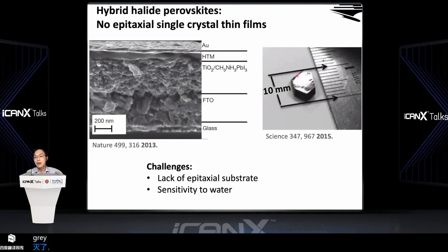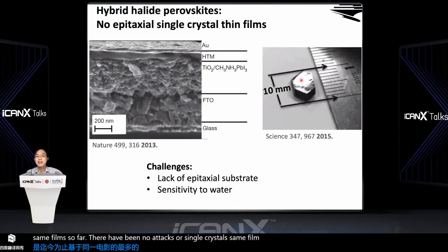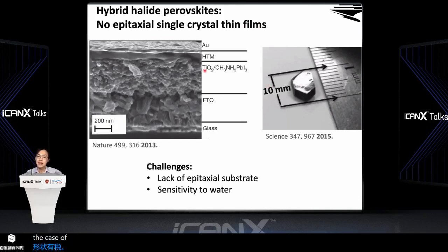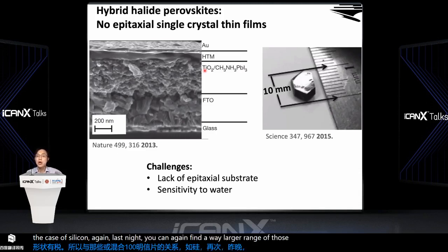And for bulk large single crystals, it's very difficult for them to be integrated onto these devices, which are mostly based on thin films. So far, there have been no epitaxial single crystal thin films based on those hybrid halide perovskites. And the challenges are twofold. The first thing is, it's very difficult to find a substrate that has an epitaxial relationship with those hybrid halide perovskites. As in the case of silicon and gallium arsenide, you can find a very large range of substrates to grow those materials, right? This is the first challenge.